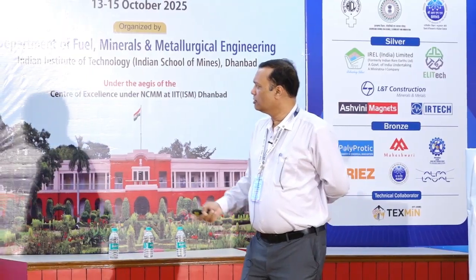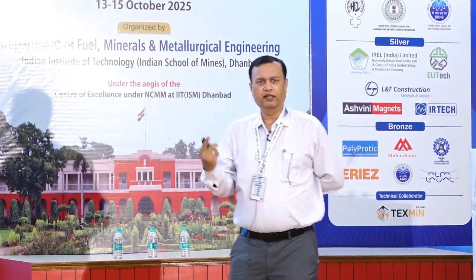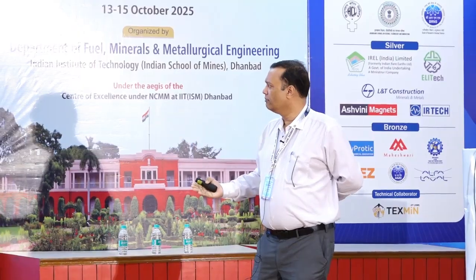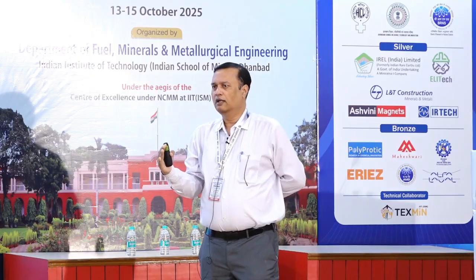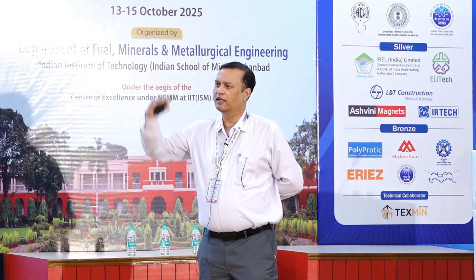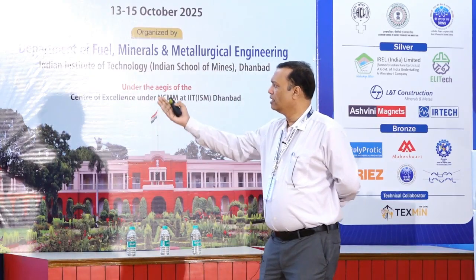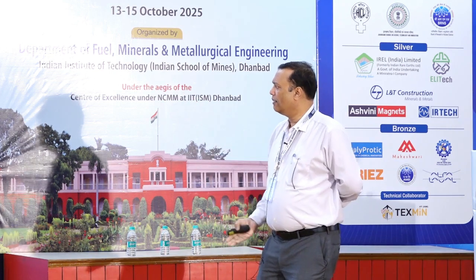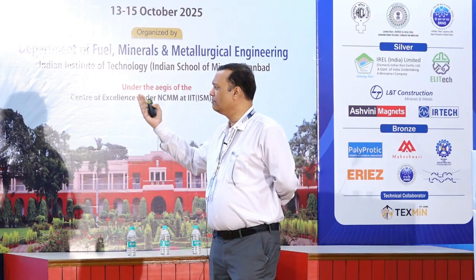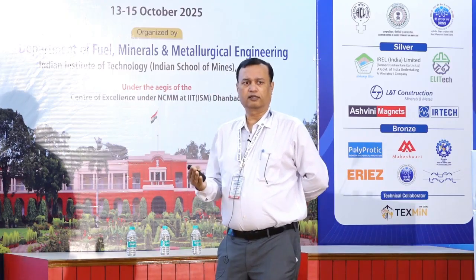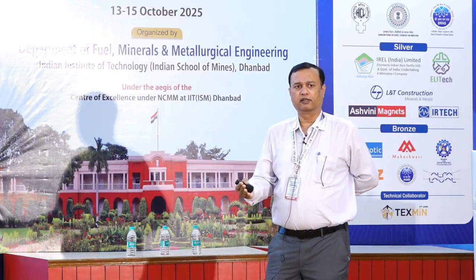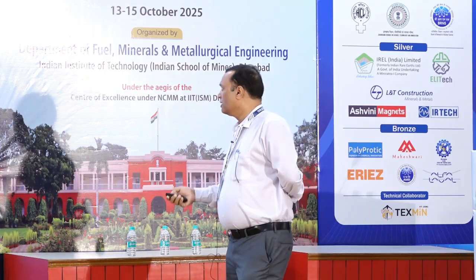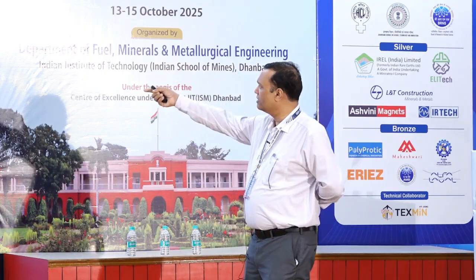The reason is that when we use this magnet, there are different types of losses. One is reversible flux loss: while the magnet is in operation, the flux of the magnet comes down, and when the operation is over, the flux is retained again. This is called reversible flux loss. It generally happens below the operating temperature of the magnet. But above the operating temperature, there is irreversible loss of flux. That means the magnet will start demagnetizing in operation. It will lose its magnetic property, and this is the cyclic demagnetization process.